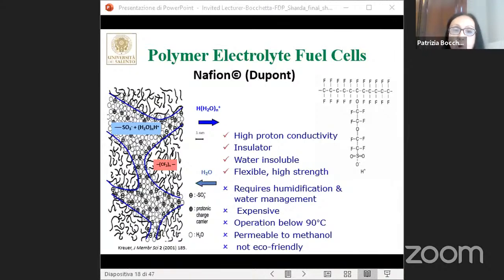The most performing working conditions of Nafion require wet conditions and a temperature lower than 90 degrees centigrade. Nafion also suffers from various problems: water loss, viscoelastic relaxation at high temperature, high alcohol permeability. This is a big drawback, especially for direct alcohol fuel cells, and moreover, they are still too expensive. Also, they are not green materials.